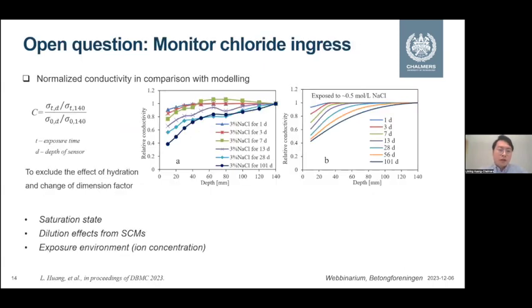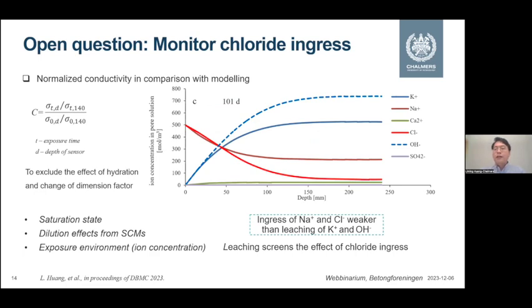This system is working well in the previous sections, but there are still a lot of open questions. We need to do more research. Here we have identified one interesting question. We try to monitor the chloride ingress of concrete samples using the ponding method. But as we can see in figure A, the normalized electrical conductivity shows a continuous decrease, which matches well with the modeling. But the real effect is that the leaching of potassium and hydroxyl ions has a strong screening effect on the ingress of sodium chloride. So we cannot really extract the chloride ingress, but instead the leaching effect, from the electrical property profile. It is also influenced by the saturation degree, blending of different SCMs, and exposure concentration.